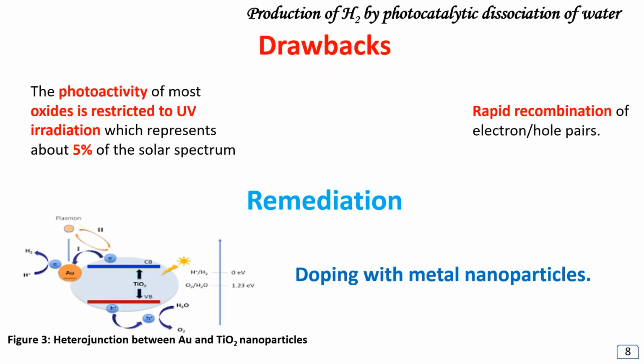The photoactivity of most semiconductors is restricted to UV irradiation, and the recombination of electron-hole pairs is rapid. To overcome these limitations, different approaches can be considered, including the deposition of metal nanoparticles. Photogenerated electrons can migrate from titania conduction band to the metal, allowing to considerably decrease the direct recombination of electron-hole pairs. The metal particles can also catalyze protons to hydrogen reduction reactions by transferring the electrons to the reaction medium.